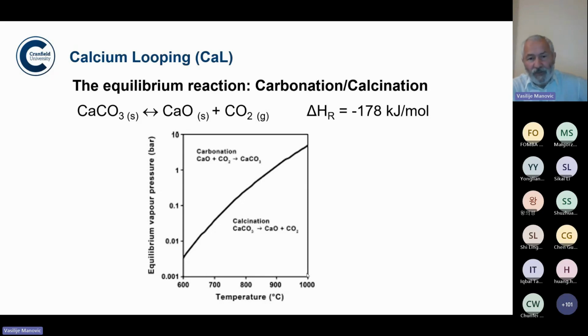With increasing temperature, the calcination reaction will be happening. With reducing temperature, we can run the reverse reaction, which we call carbonation. Usually in this process, depending on the CO2 concentration in the gas that we are processing, for example, if CO2 concentration is 10%, we can go in carbonation, that means the reaction to capture CO2, up to 700 centigrades.